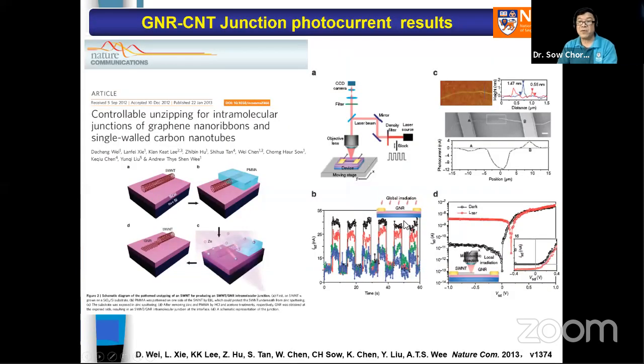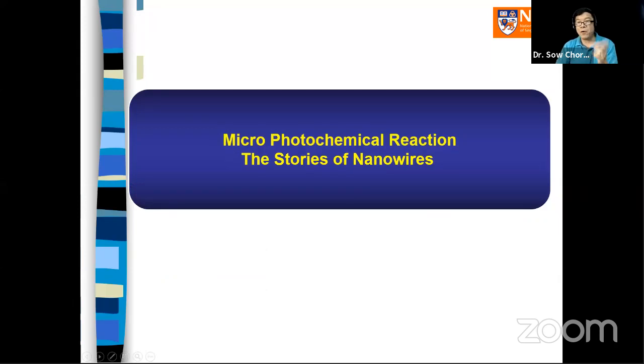So with this technique, we collaborated with Professor Andrew Wee, who is the first speaker for today's session. And we work on this particular system called single wall carbon nanotube, cover half of it, using ion to open up the single wall carbon tube, to become a graphene nanoribbon. So this is a very interesting material system. Wei Dacheng is the one who led this project. And you have literally a junction of single wall carbon nanotube and graphene nanoribbon. When we do this focused photocurrent measurement, true enough, we find that most of the response comes from the graphene nanoribbon and single wall carbon nanotube junction. So you can measure those behaviors this way. So that is the story for photocurrent measurement.